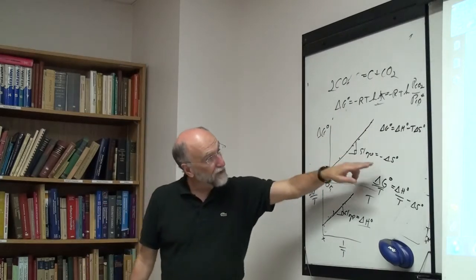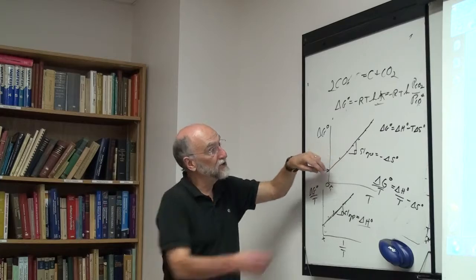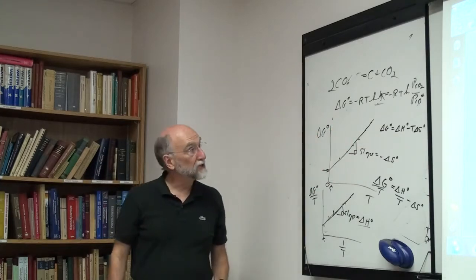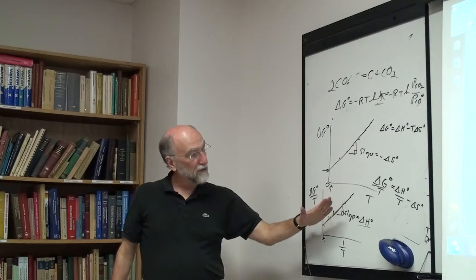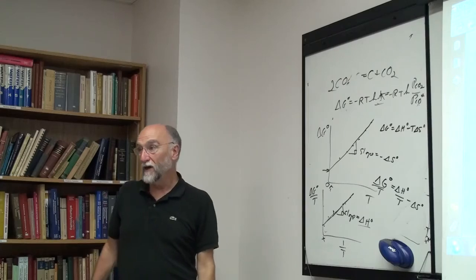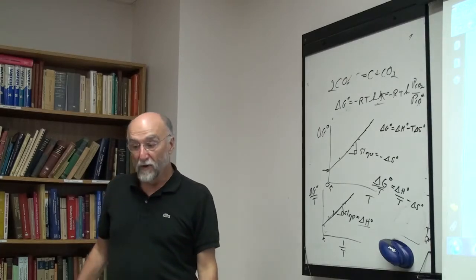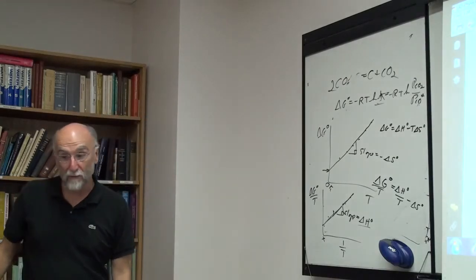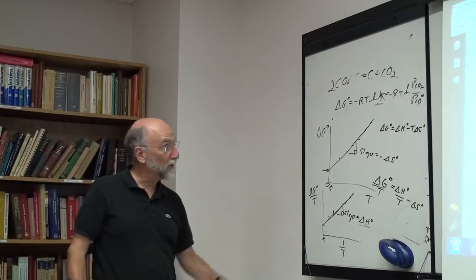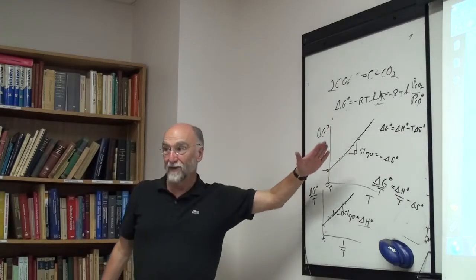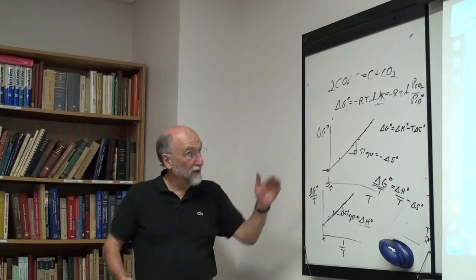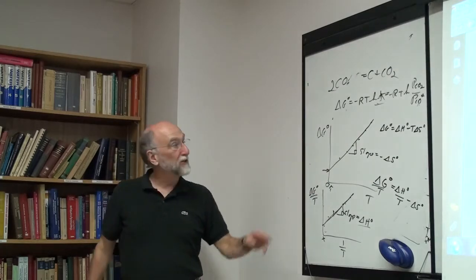Okay, so generally the electrochemical cells are good for measuring the partial Gibbs energy, the activities, RT log activity, but the second law method is not so good for measuring S and H because in general the temperature range is quite short and errors in slope can be quite high. So just realize when somebody says the H and S were obtained from electrochemical cell measurements that the question then is how accurately was the slope measured?